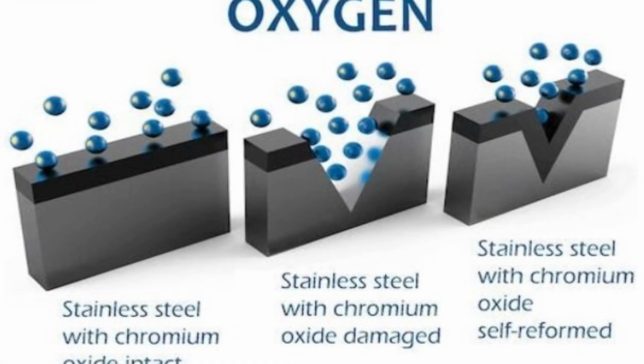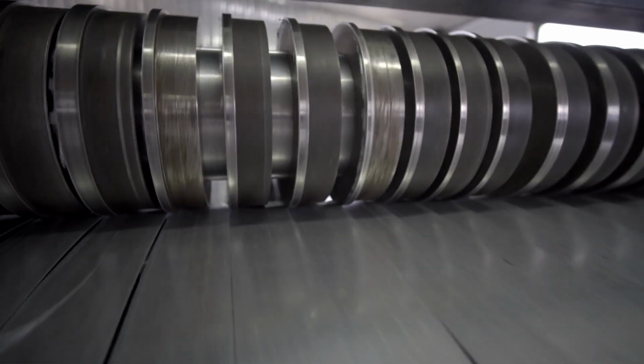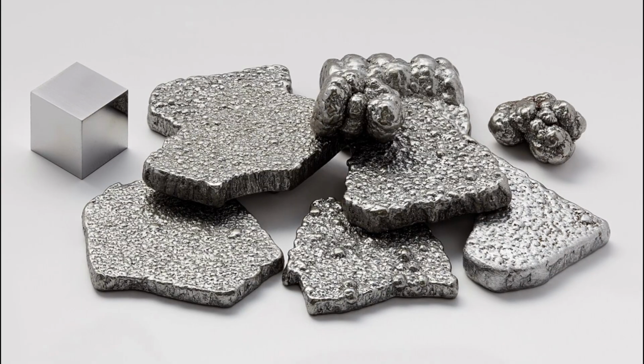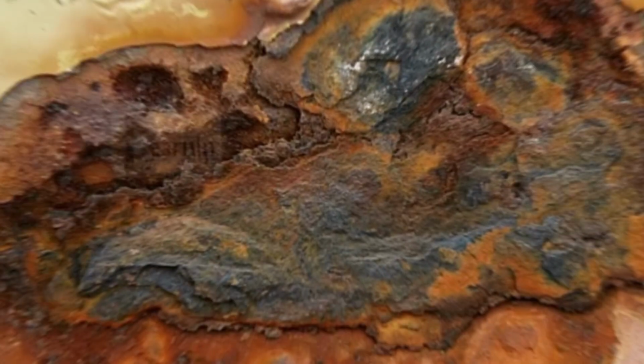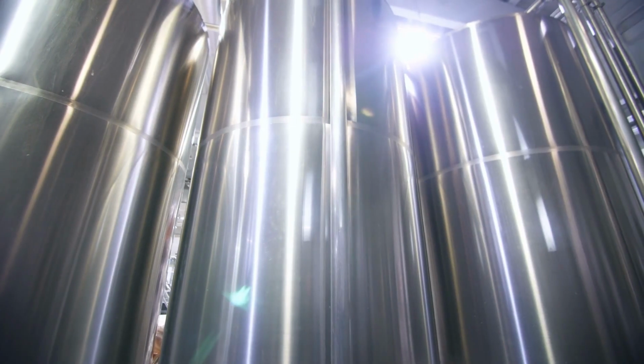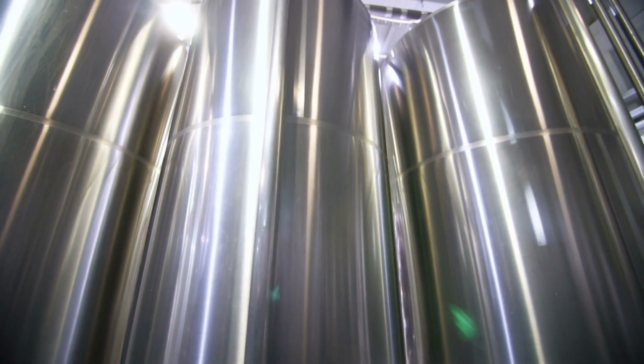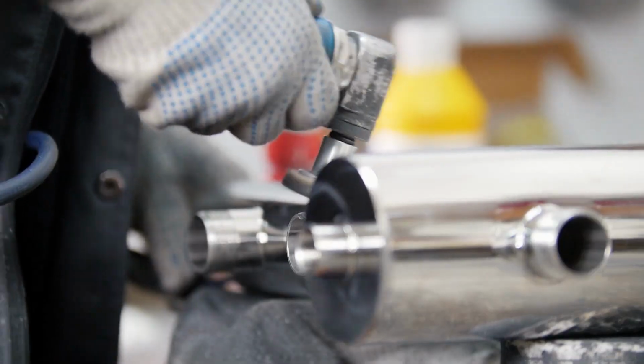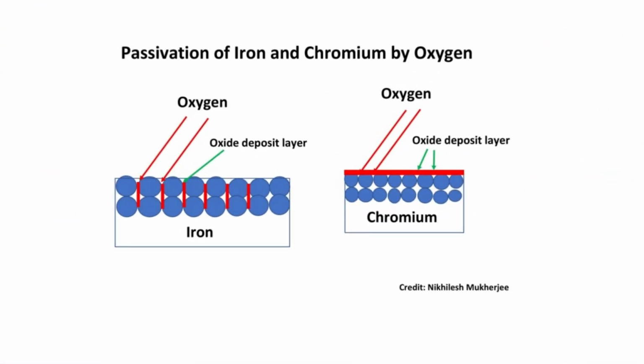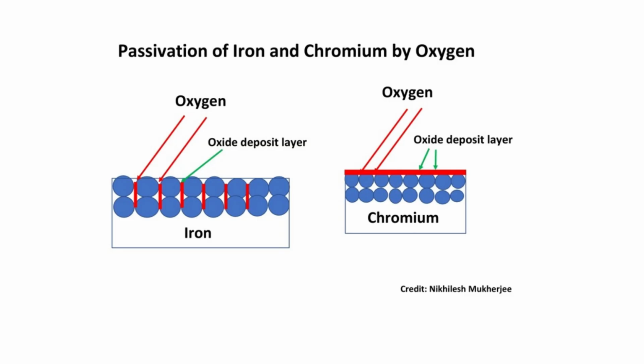That layer is chemically stable, electrically non-conductive, and physically dense enough to exclude both oxygen and moisture from the iron beneath. Unlike iron oxide, which is porous and crumbles away, chromium oxide bonds firmly to the surface and holds. The behavior that makes this genuinely remarkable is what happens when the layer is damaged. Scratch stainless steel deep enough to remove the oxide layer entirely and expose bare metal to air. The chromium in the freshly exposed alloy reacts with oxygen immediately and reforms the passive layer within seconds to minutes,